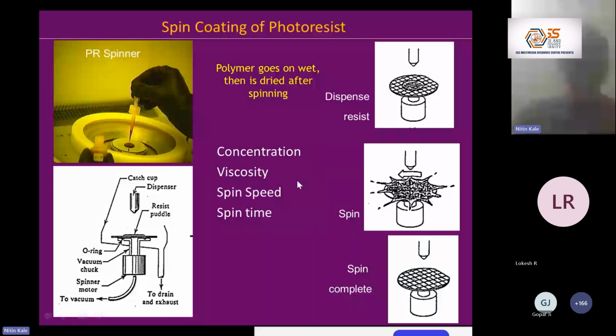And you can see here why temperature control of the clean room is important, because the viscosity of the photoresist changes with temperature. And therefore, the thickness of the photoresist is going to be different at different temperatures. So you have to be very careful. When your device sizes are so small, a minor change in the temperature will give a change in the viscosity, and all your dimensions could be lost.